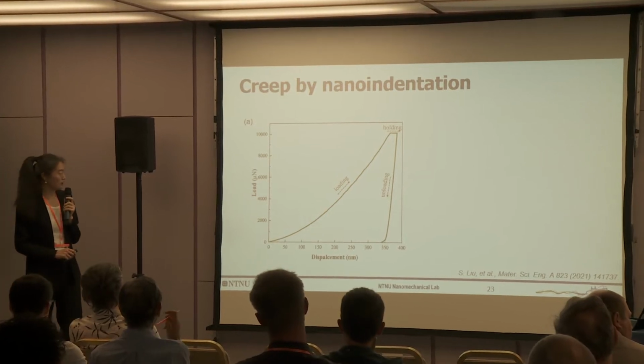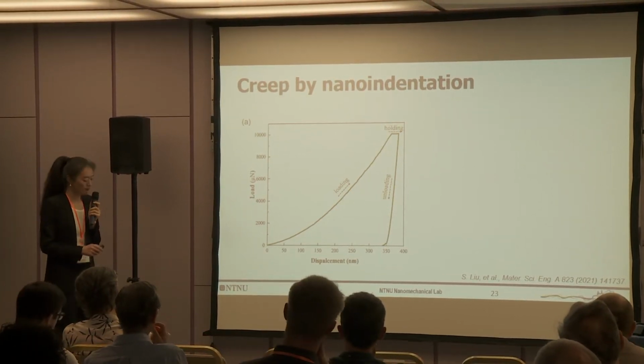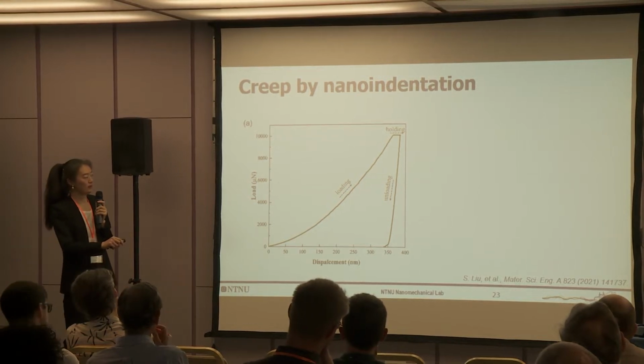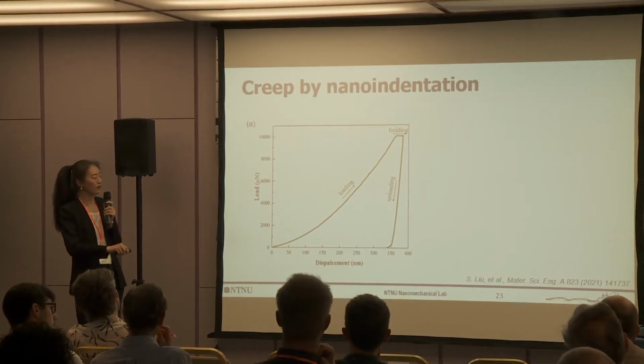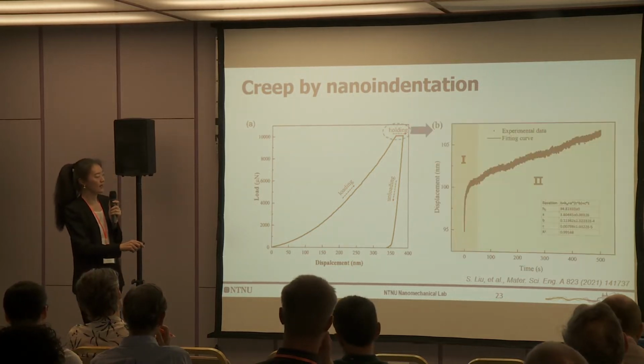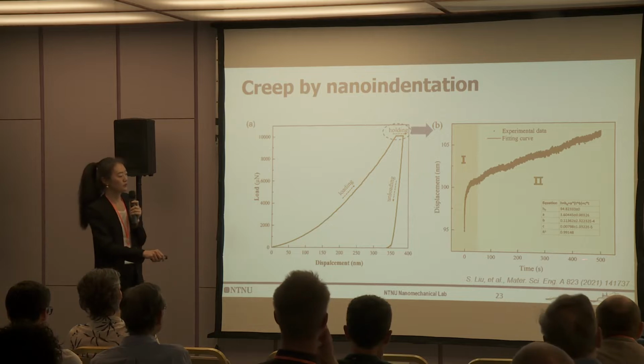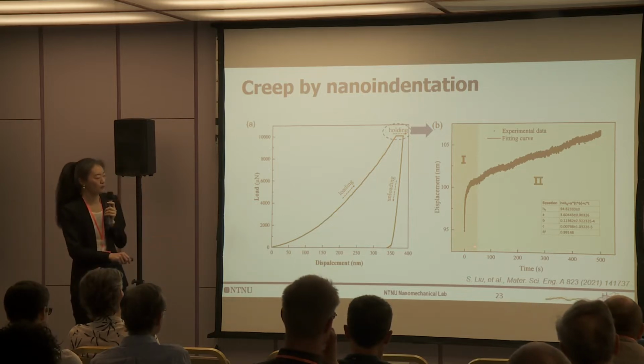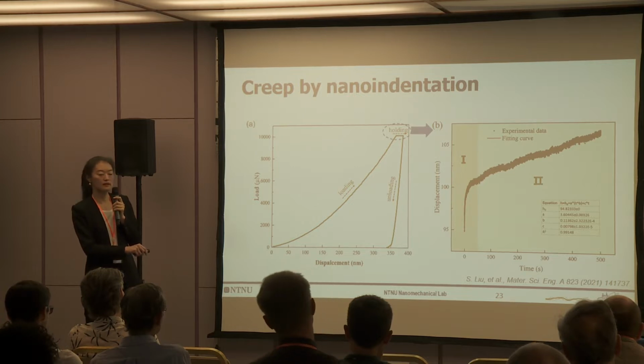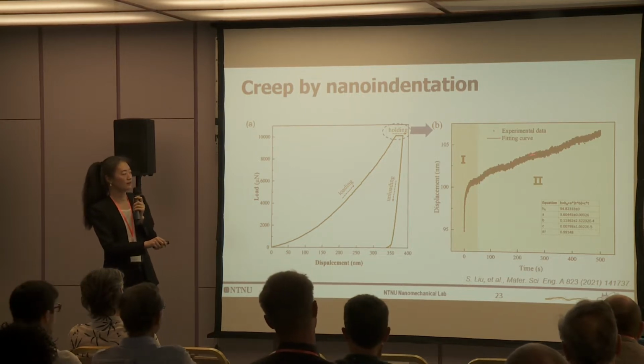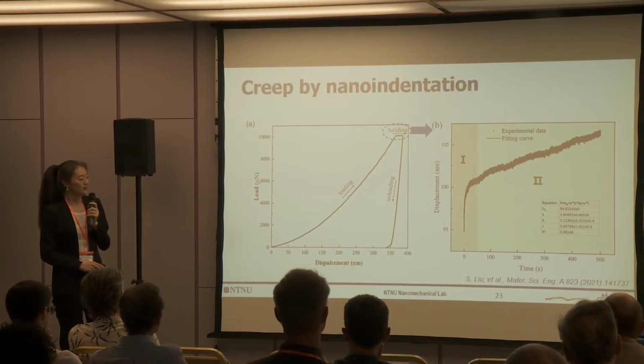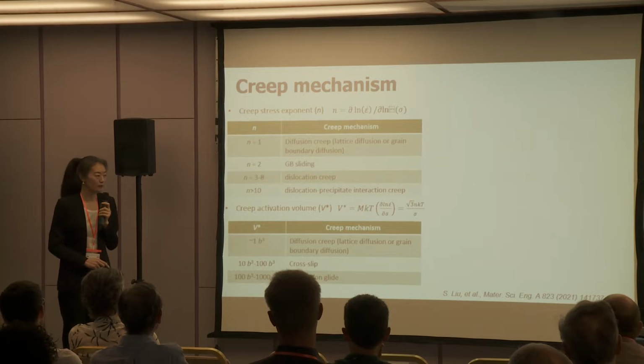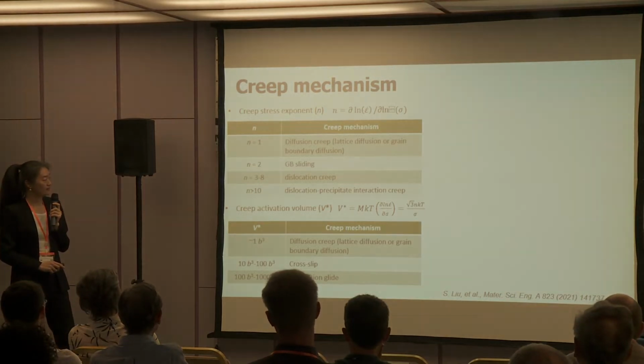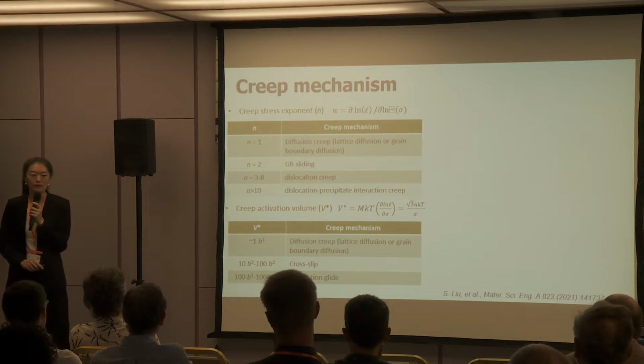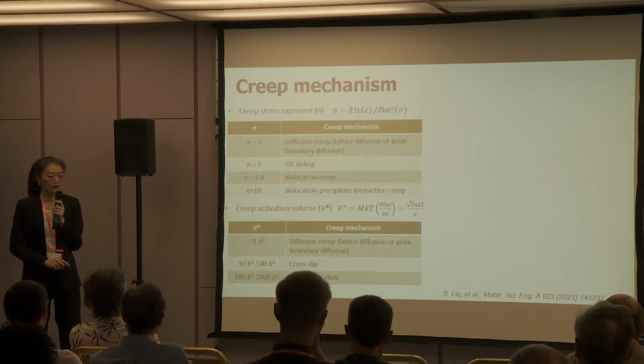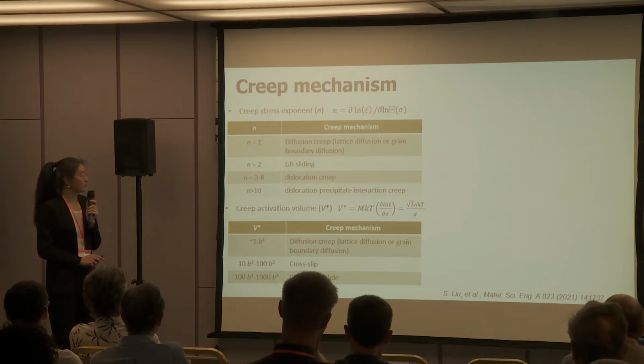Then we further focus on the creep behavior of these high entropy alloys. We apply the indentation with loading, a long holding time at the peak load, and then unloading. Then we can use this holding time to analyze the creep behavior. Here we use 500 seconds of holding as an example. We can see the creep displacement first increases dramatically, and then slows down. And interestingly, we also find that the creep is orientation dependent. So we wonder what kind of creep mechanism, compared to conventional high entropy alloys, is governing the creep behavior.